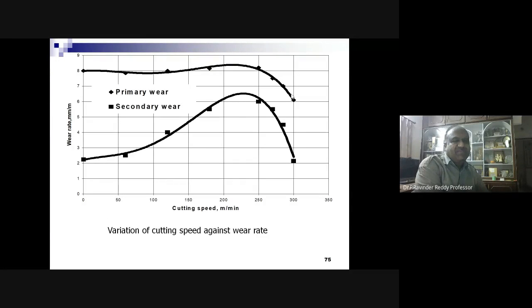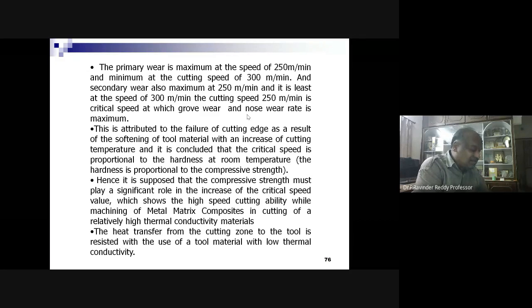If you see the wear of primary and secondary against the cutting speeds in meter per minute, you can see the primary wear is high as compared to secondary wear. And again, you can also observe both of them are increasing up to 250 meter per minute, and afterwards it is decreasing. So from those graphs, we can observe that the primary wear is maximum at the speed of 250 meter per minute, and minimum at the cutting speed of 300 meter per minute. The secondary wear is also maximum at 250 meter per minute, and it is least at the speed of 300 meter per minute.